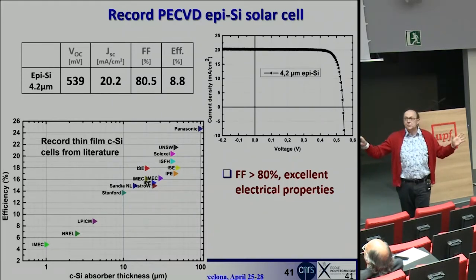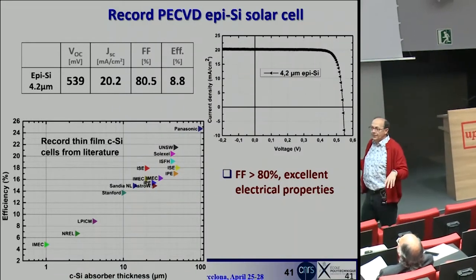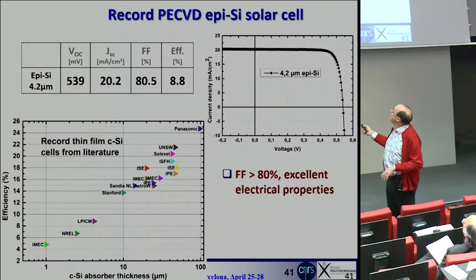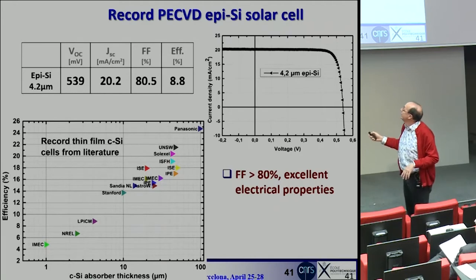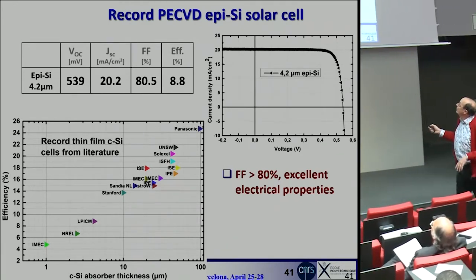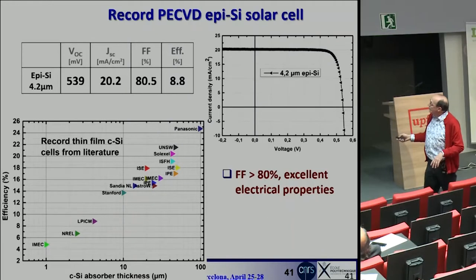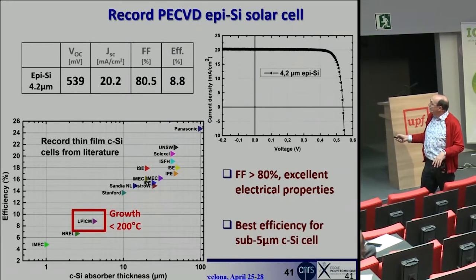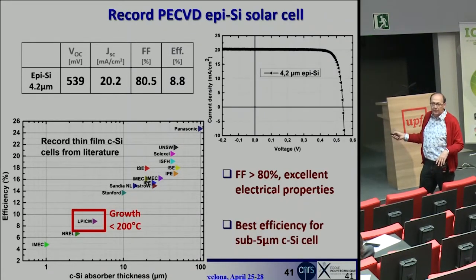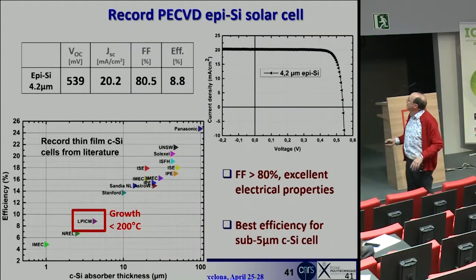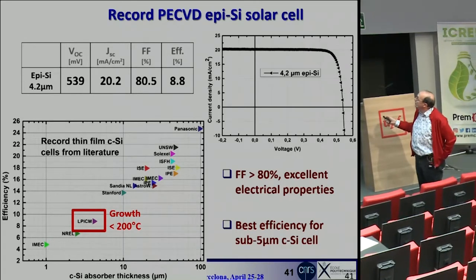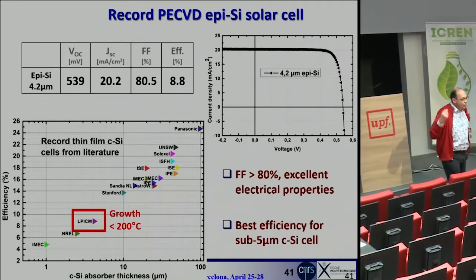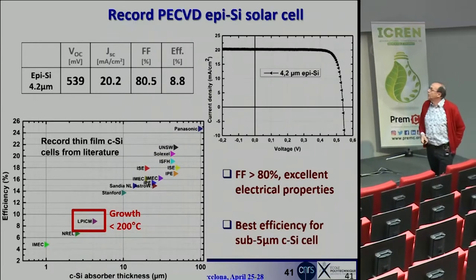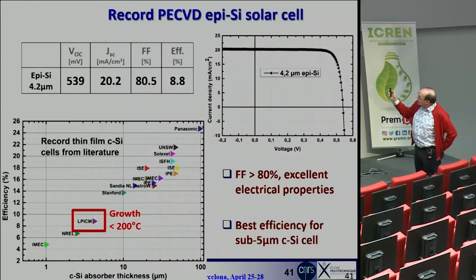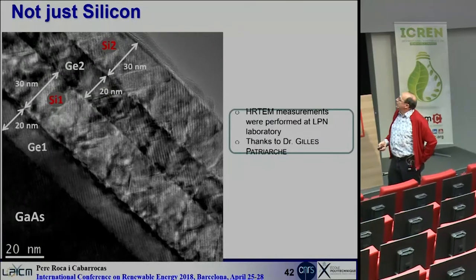In photovoltaics, people only care about efficiency. And I always say, I don't care about efficiency, I care about fill factor, current, and voltage. What you see here is that we have low efficiency, 8 to 9%, but if I put this in the context of the thickness, then we are pretty well placed in this chart of efficiency as a function of wafer thickness. So we have very good fill factor. It means that this epitaxial layer has very good electronic properties, and we have the best efficiency for this sub-5 micron cell.